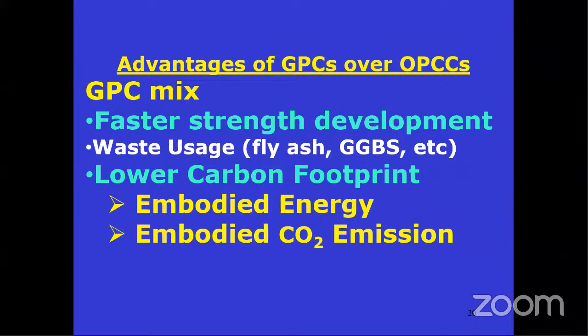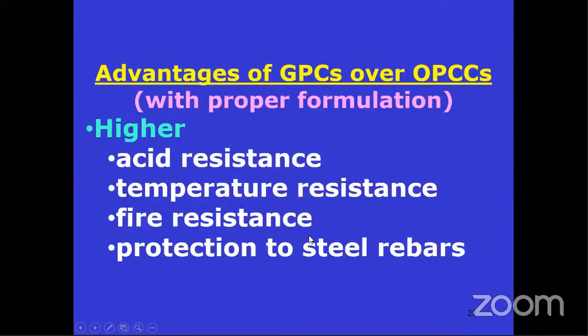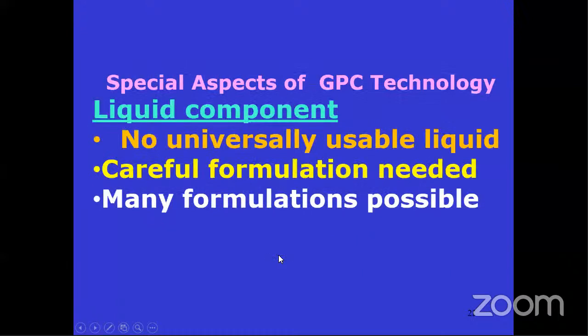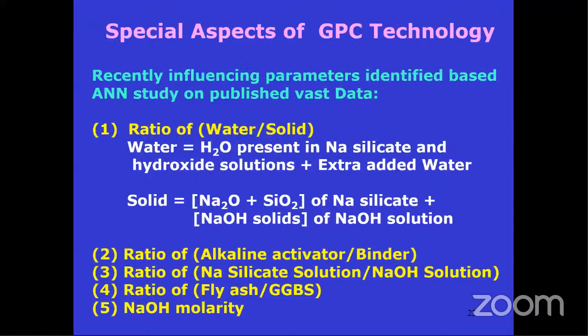Okay. And these are only two slides. I want to tell this fact. We have done numerical value calculation for all this. It is not from the literature. So strength development, you have studied. This combination also we calculated actually. And we have studied the acid resistance, temperature resistance, fire resistance, and steel corrosion. And what I wanted to tell was, these are the different parameters that control the concrete properties.